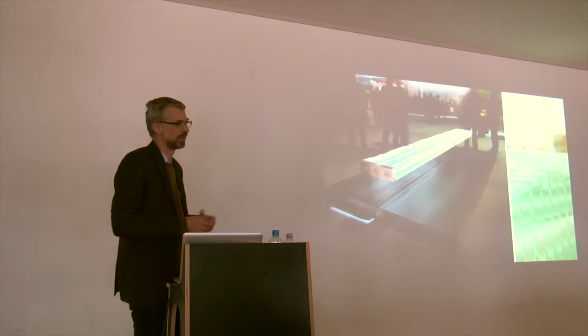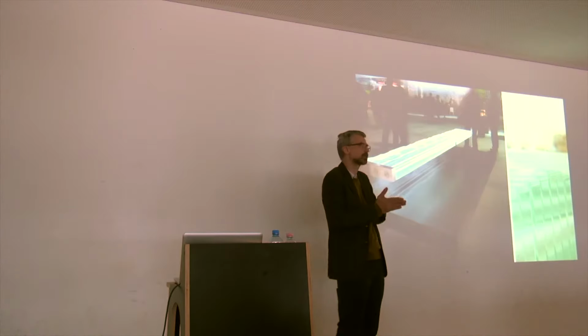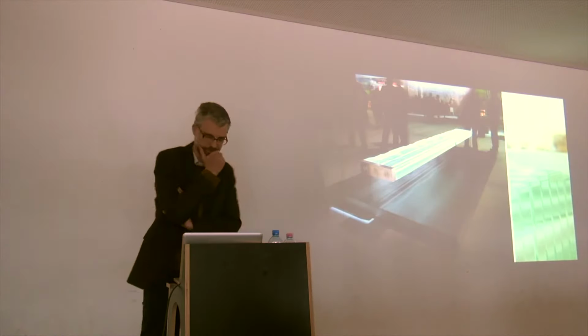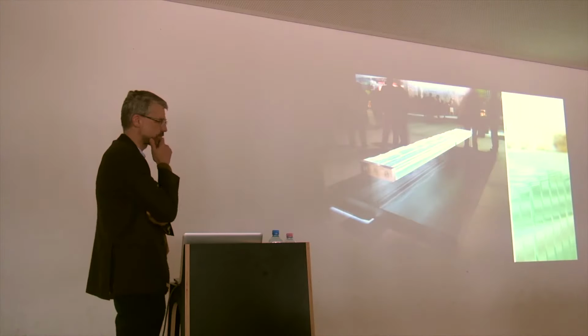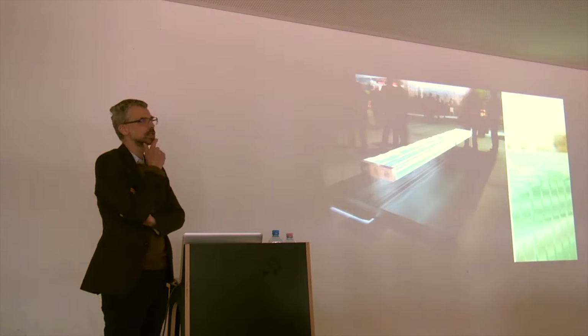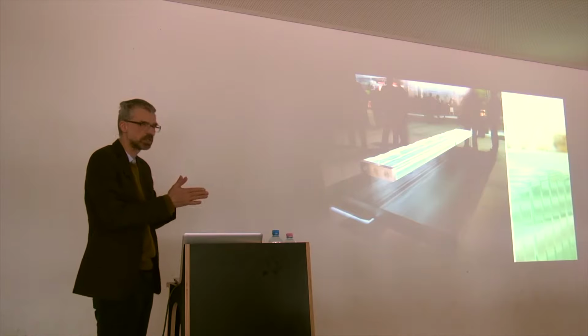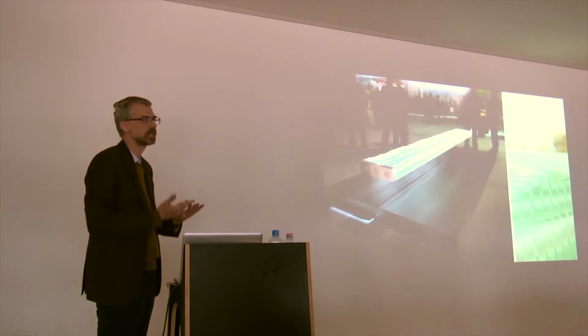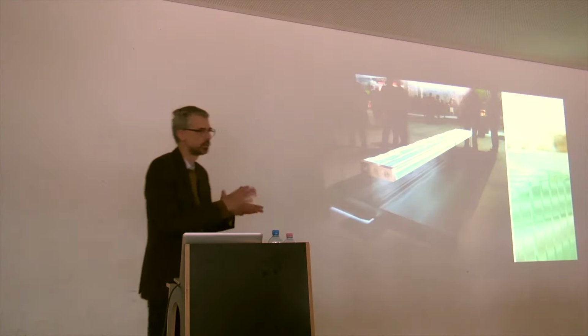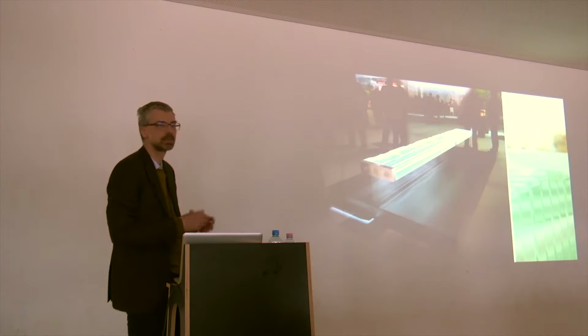with a relatively high force in order to make sure that the joints are not opening up and all surfaces are under continuous compression. And this is done with these three pre-stress cables of a very high grade metal to introduce those pre-stress forces. And we did a number of tests on introducing interlayer materials or using tempered glass. And it was clear that any sort of interlayer material you would traditionally use between glass would decrease its load-bearing capacity, as the controlled way of flowing forces through that stack would be dependent on its plastic deformation. So we just basically have a dry stack of glass. You can unbolt the nuts and you can take the entire structure apart.